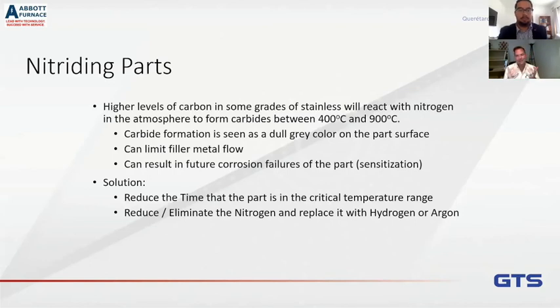Now, why is this a big deal? Well, the problem is if you nitride the surface while you're entering the furnace, it acts just like an oxide contamination and the filler metal won't flow. But if it doesn't happen in the front, because you're going from 400 to 900, it could happen in the back.